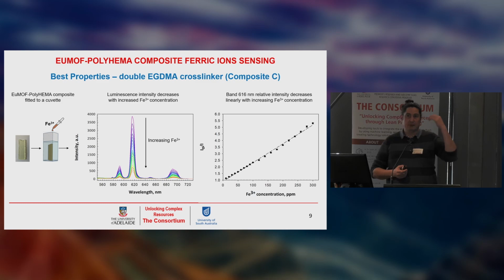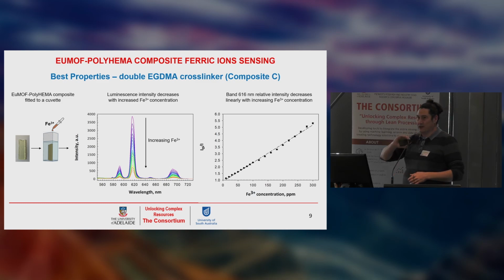So how does it respond to iron? Well, its response to ferric ions is beautiful. You get this very nice linear response to different ferric ion concentrations. So in the presence of the iron, when the composite is illuminated or excited at 320 nanometers, you can see that as we increase the iron, the emission from the MOF actually decreases. So you get this beautiful linear relationship between the iron concentration and the change in intensity of the emission. This is just the original starting intensity in the absence of the iron, divided by the intensity in the presence of the iron. So it relates to the decrease. So with increased ferric iron concentration, you can see this linear response.